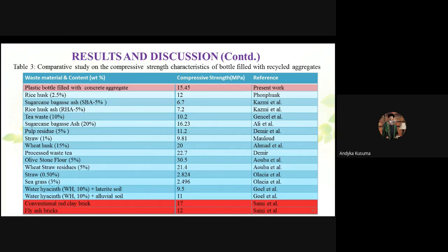For a fly ash brick, the average compressive strength value is 12 MPa, and for conventional red clay bricks it is 17 megapascal. So the compressive strength value of the developed specimen was much better than fly ash bricks and is comparable with that of conventionally used red clay bricks.